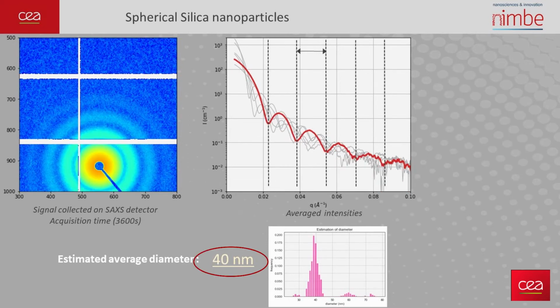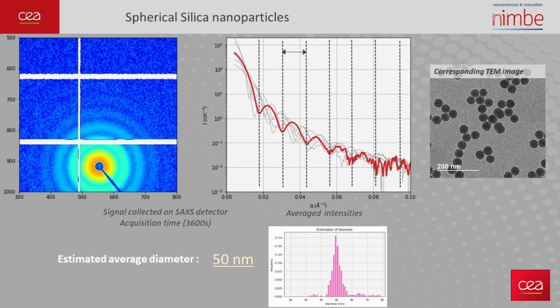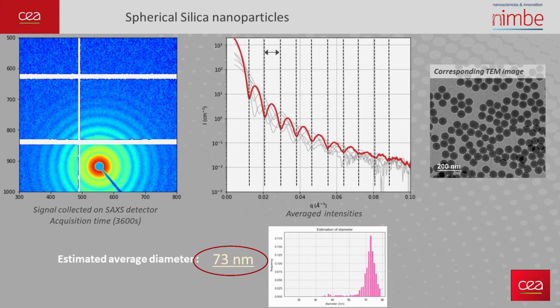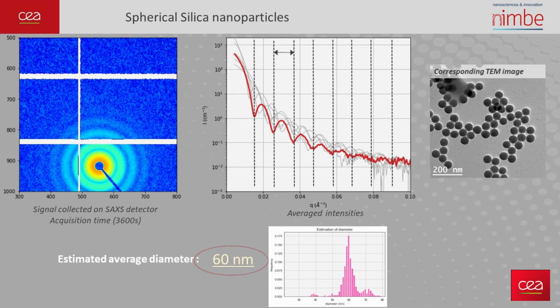In the NP-size project, we have worked with monodisperse spheric silica nanoparticles. Measurement of such sample gives typical periodic oscillations, which strongly depend on the nanoparticle size. We use a dedicated software to analyze the signal. From such scattering curves, the size and polydispersity of the silica nanoparticle is obtained with a very good precision. The precision is less than 1 nanometer. The concentration is related to the intensity collected by the detector.